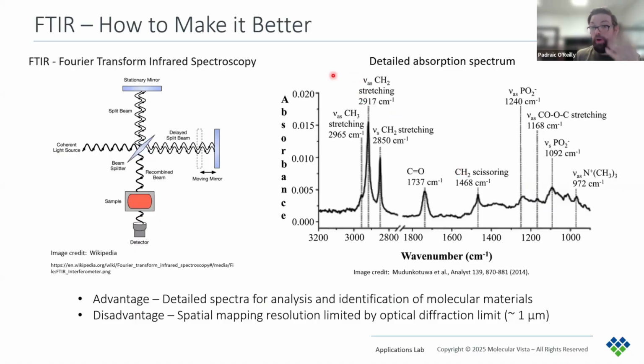So why IR? To gather molecular information, FTIR is typically used. It's really, what they say, the workhorse of the analytical chemistry lab. So all molecules will have a unique chemical fingerprint based on the vibrational modes of the atomic bonds present. So the advantage of IR is that you get detailed spectra for analysis and identification. And also with large databases for comparing spectra with. Now the disadvantage is that the resolution is diffraction limited. And this is where we turn to PiFM to determine molecular information beyond this diffraction limit.